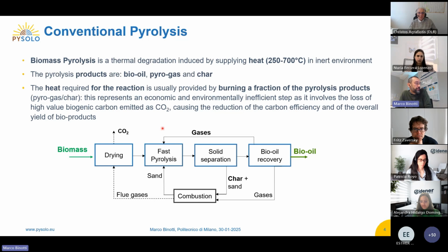As reported in this schematic, usually the biomass is dried, then you have the pyrolysis reaction. The heat supporting the pyrolysis reaction, which is endothermic, is provided by the combustion of a fraction of the products. Typically the char, and maybe a fraction of the gases, is used to heat up the pyrolysis reactor. This is a loss of carbon, which is emitted as CO2. So it's a reduction in what we call carbon efficiency and in the overall yield of bioproducts.